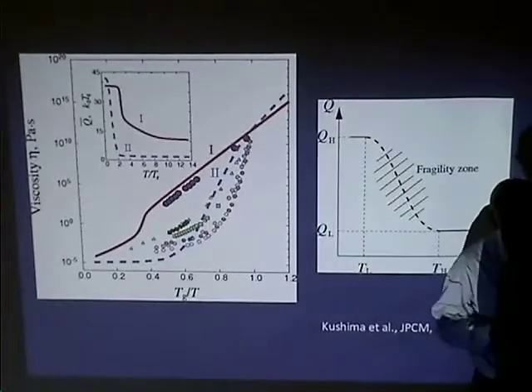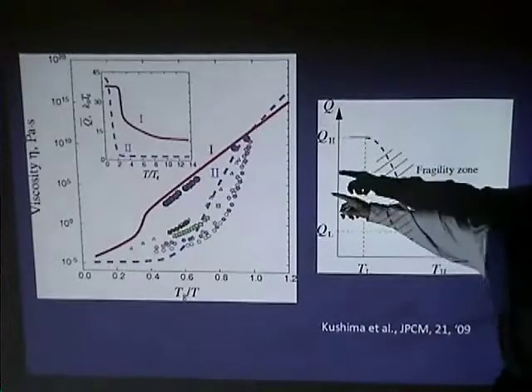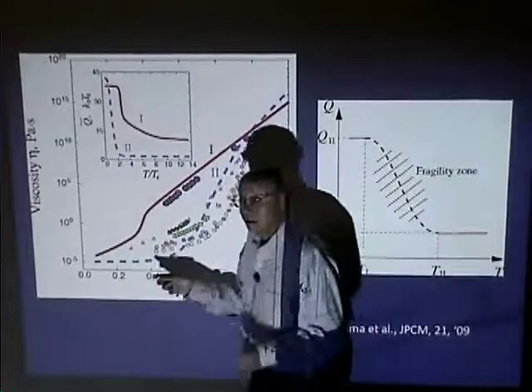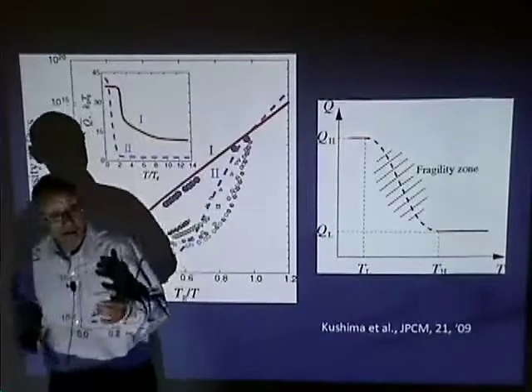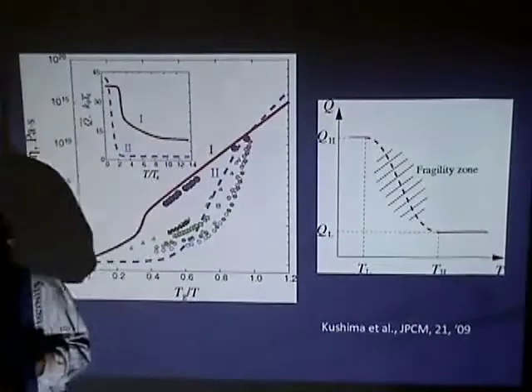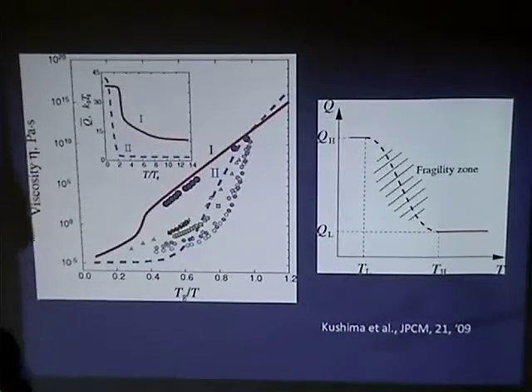So our final conclusion is that to reach this kind of discussion, you need thermodynamics, which comes from inherent structure, which has to do with the local minima of the basins. But that's not enough. You also need the saddle points because you need to hop over them.